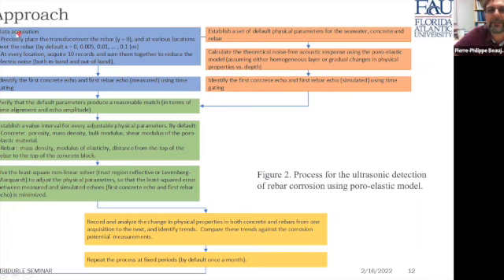So let's start with the data acquisition. We precisely place the transducer over the rebar at a fixed value of Y, and we move the transducer at various locations along X. Typically, we move the transducer by 5 millimeters at a time. At every location, we acquire, as of now, 10 records and sum them together after careful time alignment to reduce the electric noise, both in band and out of band.